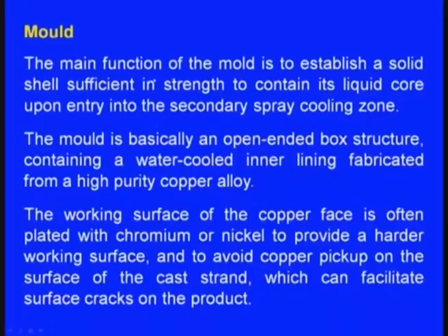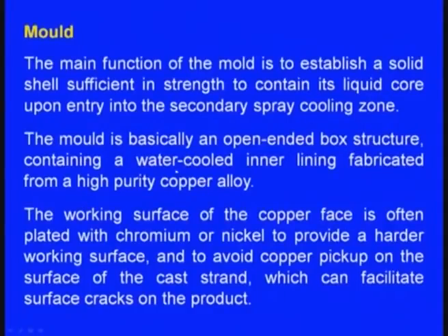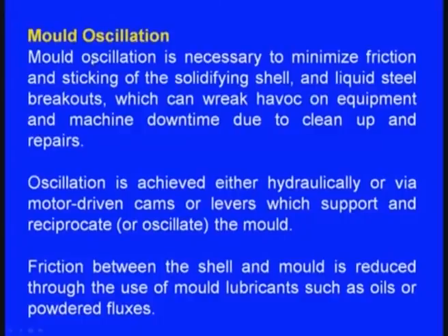Next one, mold. The main function of the mold is to establish a solid shell sufficient in strength to contain its liquid core upon entry into the secondary spray cooling zone. The mold is basically an open-ended box structure containing a water-cooled inner lining fabricated from a high purity copper alloy. The working surface of the copper face is often plated with chromium or nickel to provide a harder working surface and to avoid copper pickup on the surface of the cast strand, which can facilitate surface cracks on the product.